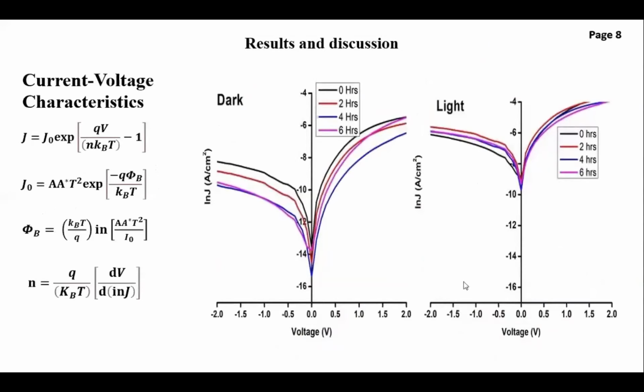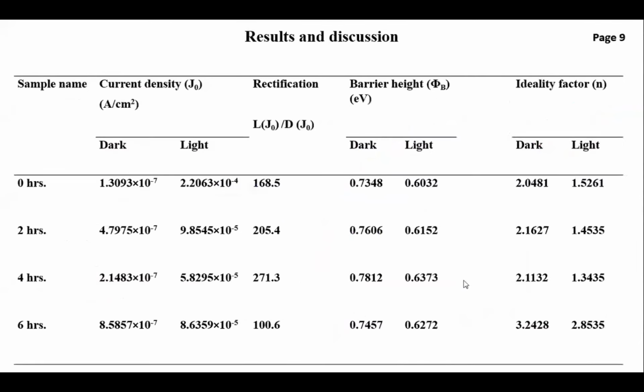The current-voltage properties were used to determine the barrier height and the ideality factor. The equation J equals J naught exponential of qV over n kBT minus 1 was used to find the barrier height and the ideality factor. As we can see from the graph, the barrier height and the ideality factor were determined. The values of the barrier height and the ideality factor were tabulated in the table here.